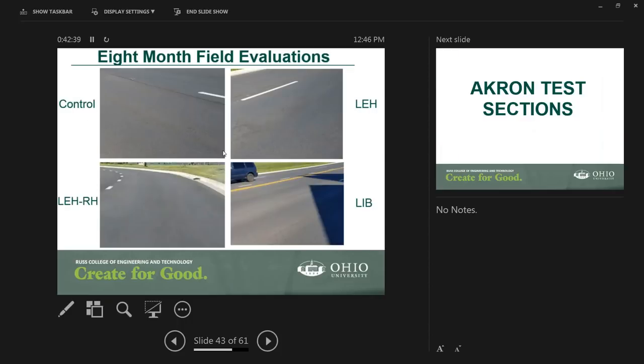Now, those pictures were taken 8 months ago, but just passing through that roadway less than a month ago, it's the same thing. There is really no issues so far. So after about, I would say, a year and a half, there were no issues in terms of any cracking or potential cracking. At the time when we did a full evaluation, the PCR value was technically 100 because there were really no cracks or any type of distresses. For all sections so far, there are no problems.